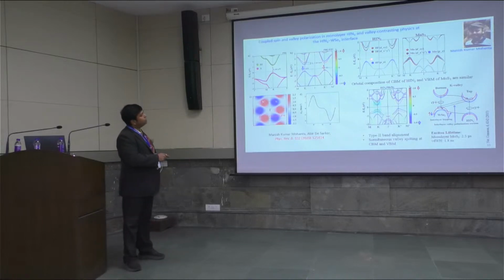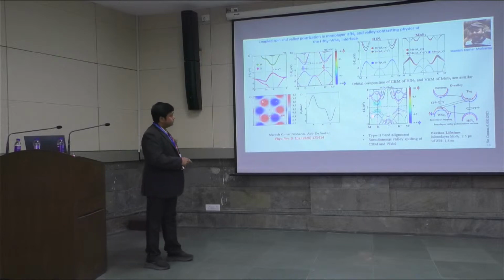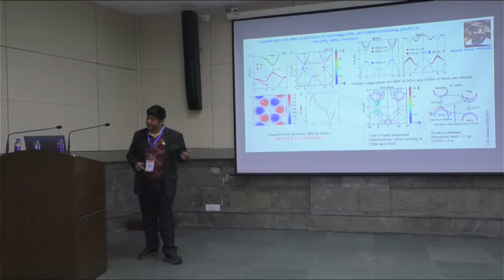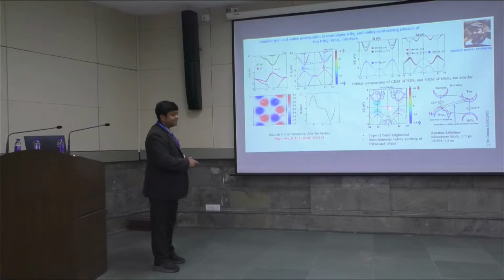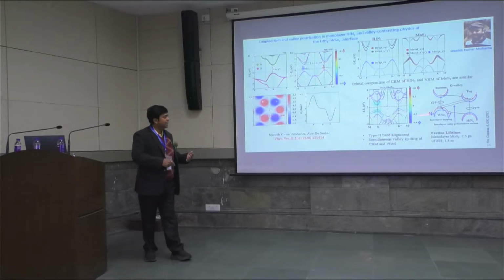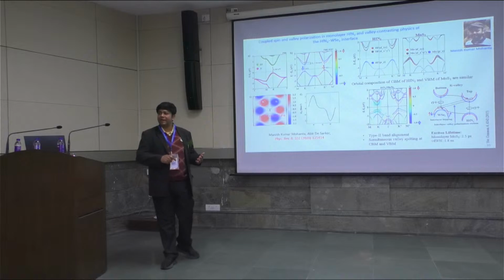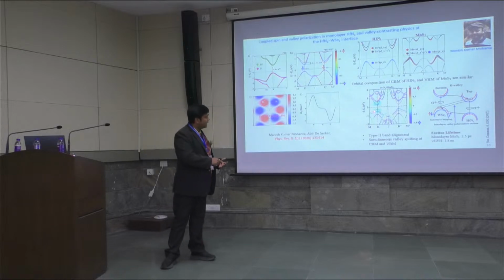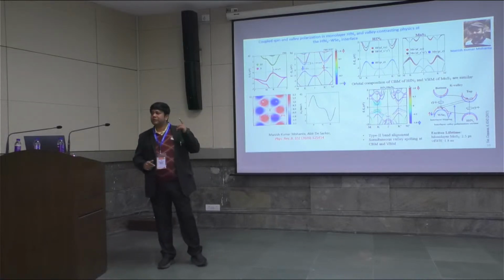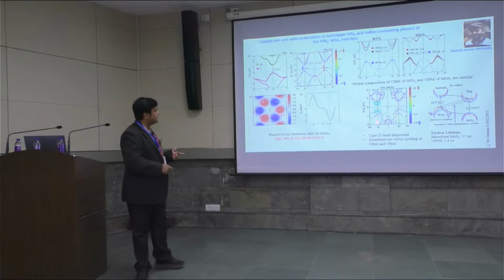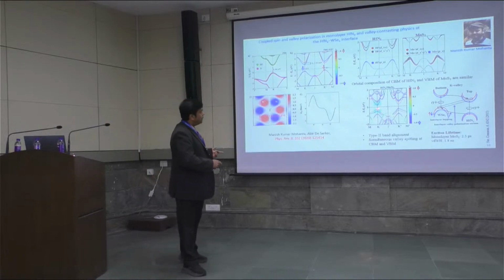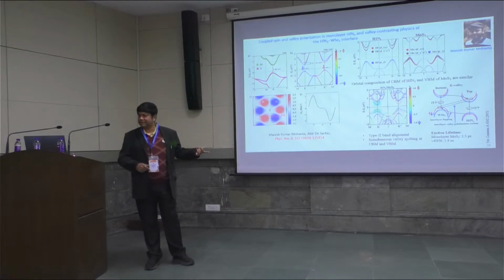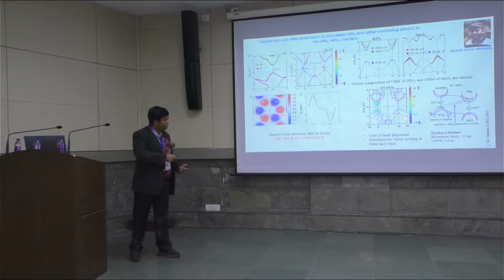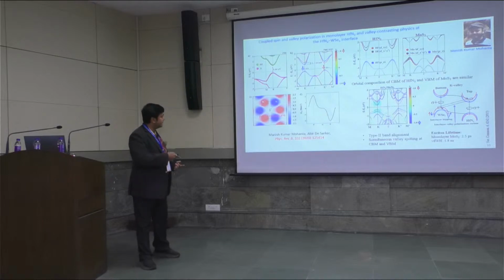So when the HfN2 monolayer is stacked on top of a molybdenum telluride, to form a van der Waals hetero bilayer, a type 2 band alignment arises in it. As a result, we are able to realize a large Zeeman type valley spin splitting at both the conduction band and the valence band. So this will be ideally suitable for valleytronics applications, because in a van der Waals hetero bilayer one can prolong the lifetime of valley polarized excitons. I will talk about the type 2 band alignment in the next few slides.